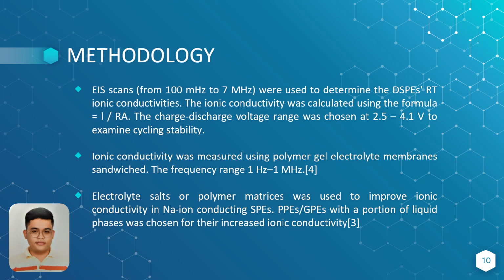The next methodology is that ionic conductivity was measured using a polymer gel electrolyte membrane sandwiched between two 1.24 cm² cross-sectional area stainless steel blocking electrodes. A 10 mV alternating perturbation voltage was applied across the SS-electrolyte-SS cell configuration, and the real and imaginary impedance were measured over the frequency range 1 Hz to 1 MHz.